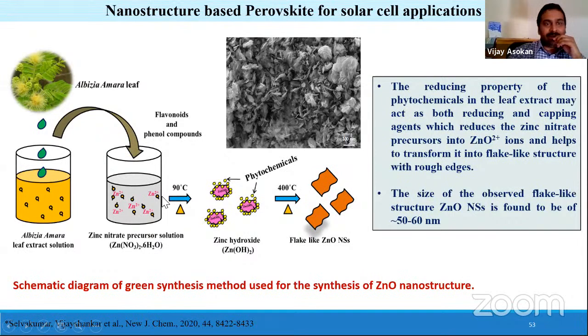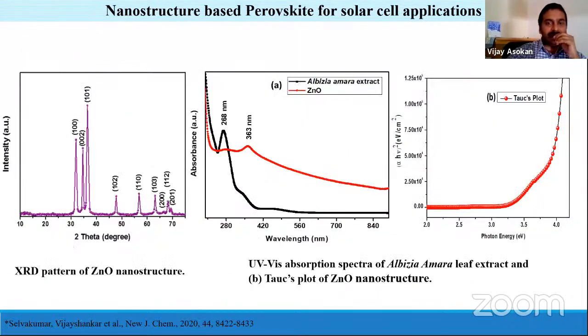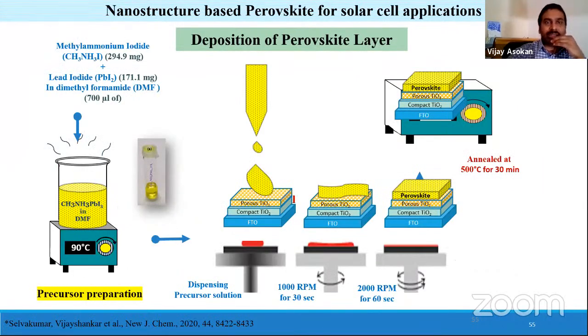Okay. So we have used a green synthesis of making zinc oxide nanoparticles from a leaf, and it's published in the New Journal of Chemistry, a Royal Society of Chemistry journal, which we published very recently. So you can see how we synthesize such zinc oxide in this paper. We have used XRD and UV analysis to show how these zinc oxide nanoparticles were synthesized. And we have deposited the perovskite layer by our routine way, which we already used in other research, shown here.